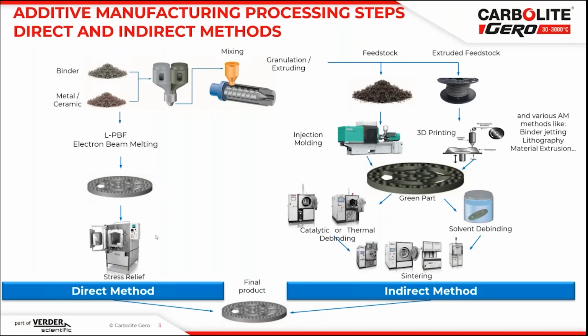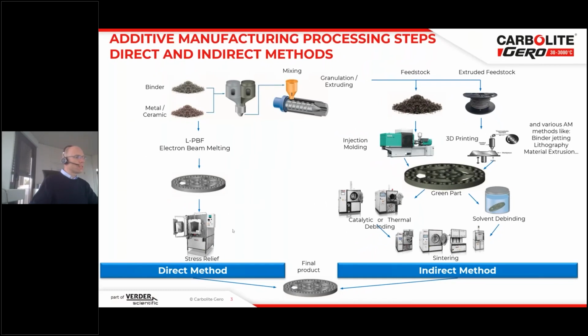And that is basically the reason why you need to have a post-processing step in order to relieve the stress from the material which comes out of the manufacturing process. And also this is a heat treatment step, and here we have additional solutions from Carbolite Gero. So in additive manufacturing, you see heat treatment is really needed, although it's not in the focus of many users, but it's a very important step. And if you don't have precise machines, the best printer cannot manufacture good parts.